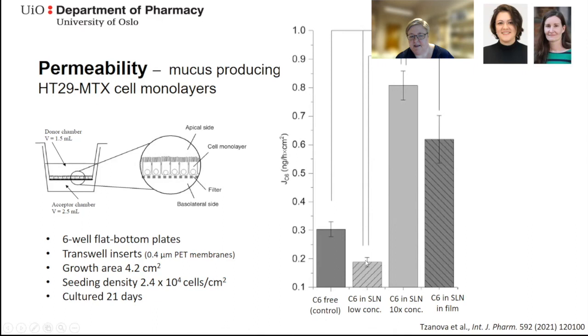And then we looked at the same concentration of the SLNs as we have in the films, and a 10 times higher SLN concentration. And the flux was not surprisingly much higher when we increased the concentration of the SLNs. But also the flux was higher from the films as compared to the particles as such.